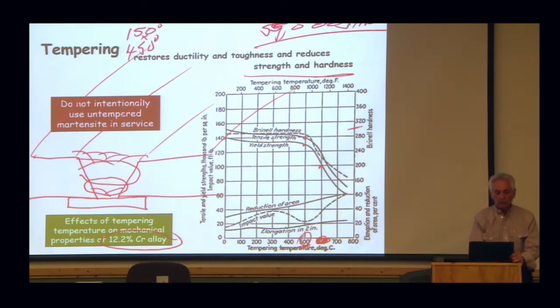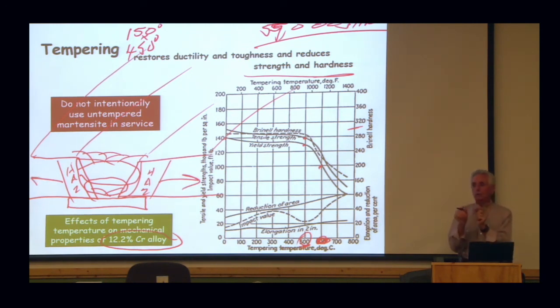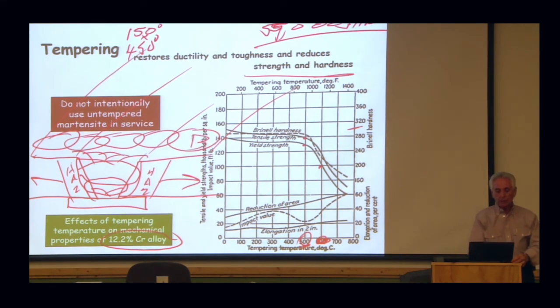Anyway that's why we do welding procedures and that's why we follow the welding procedures because if we don't follow them we're going to take the properties of that material that they spent a lot of money to get, we're going to take them away. Where? It's going to be in that heat affected zone and that heat affected zone is out here. If he welded with the right filler metal the weld is okay and everything from here out is okay but it's that one little eighth of an inch heat affected zone that they just destroyed by doing that. It didn't mess the weld up, it didn't mess the base, but it's that chain.